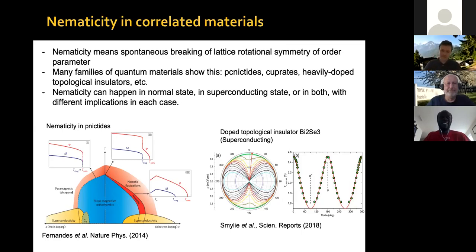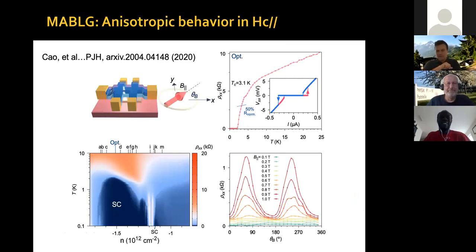Now, let me tell you about our experiments. Again, this paper is posted on the archive. So this is a magic angle graphene device, okay? We cool it down in a cryostat where we're able to apply an in-plane magnetic field and vary the magnitude and the direction of the in-plane magnetic field, okay? This is done with a vector magnet. Now, this is one of our highest TC samples, 3 Kelvin, as measured by 50% normal state resistance, okay? With beautiful switching currents, beautiful superconducting curves, okay?